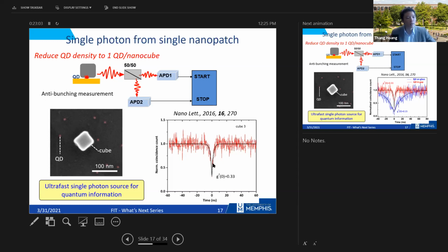The curve here is showing that there's a dip at the 0 time difference between the two detectors. The dip tells you that at the 0 time delay between the two detectors, there's no coincidence. That means the photon has to split into either APD1 or APD2, with two detectors. It can come either to APD1 or APD2, but it cannot come to both APDs at the same time. So at the time delay of 0 between the two APDs, you should get no photon, and that's exactly what we're seeing here.